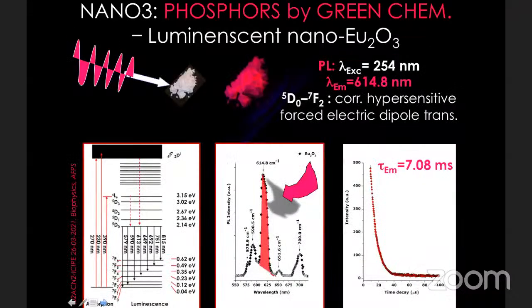And the most important is to see how this europium oxide luminesces as a phosphor. So you come with an excitation in the UV, at 254 nanometers. When you excite it, it emits in the red, this powder. And as you can see, this emission is strong and very well identified. It's the 5D0 to 7F2, the hypersensitive forced electric dipole transition.